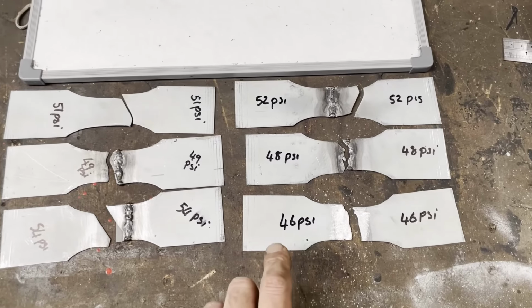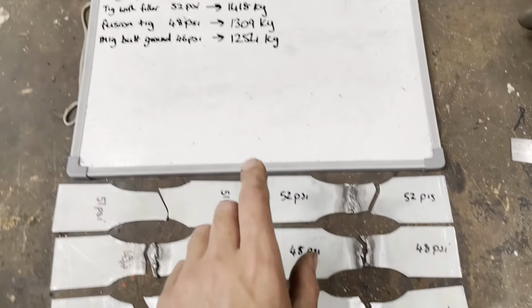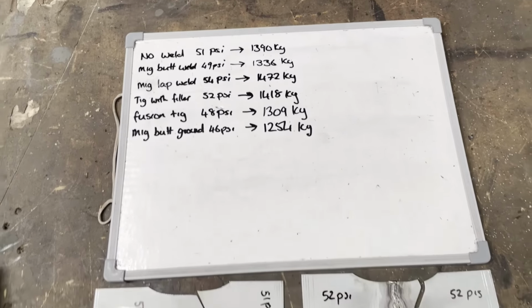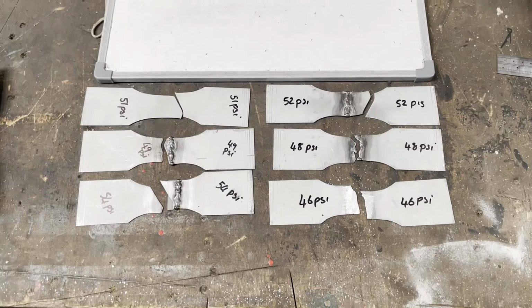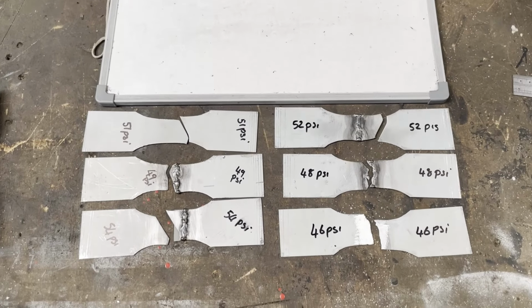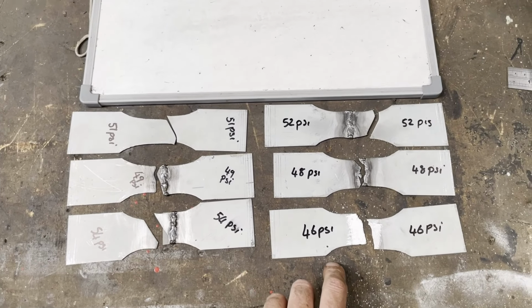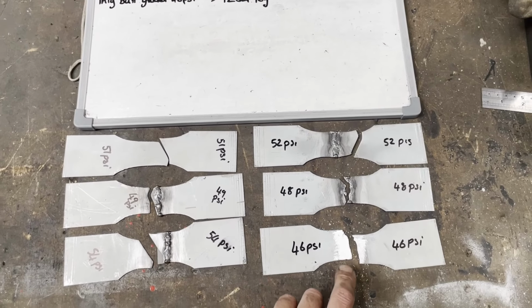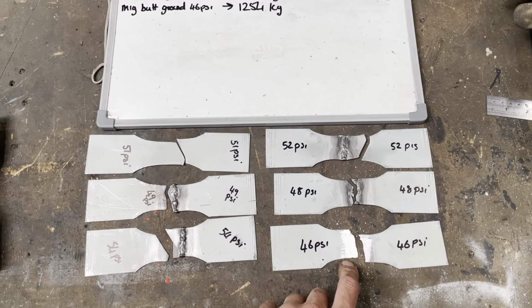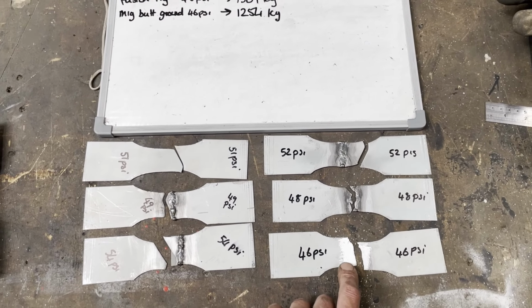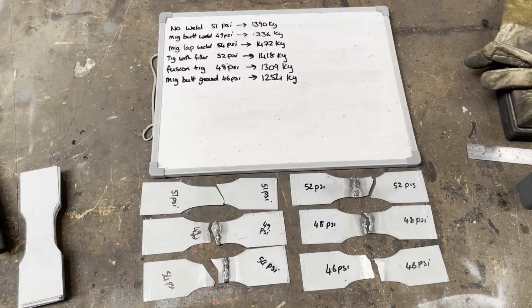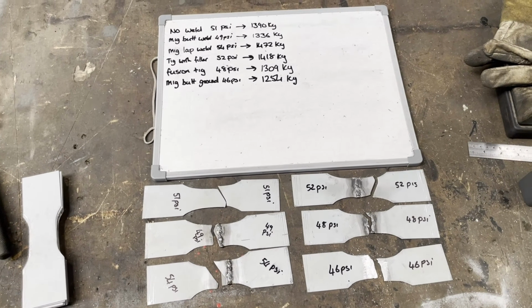A MIG weld ground down then, 46 psi, that is 1254 kilograms, and that is the weakest so far, but we're not talking very much at all. I'm really quite pleased with that. I grind down my MIG welds, and I'm pleased to see that I'm not affecting the strength by very much. Let's have a go at a spot weld.